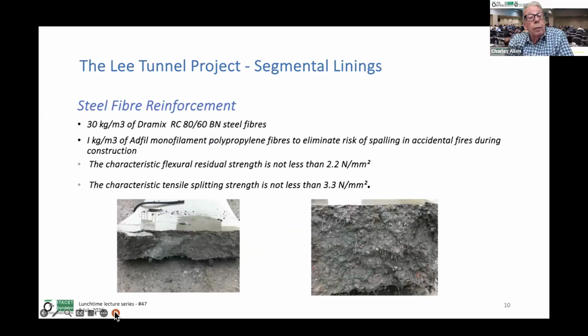The steel fibre reinforcement, we only used 30 kilos of Dramix 80/60 BN steel fibres. We used 1 kilo of Adfil monofilament polypropylene fibres. This was to eliminate the risk of spalling in accidental fires during construction. Obviously, we were not subject to road or rail fire curves. And the characteristic flexural strength was not less than 2.2, and the characteristic tensile split strength was not less than 3.3. Obviously, one of the first things we did during initial production was to break a couple of segments in half and look at the fibre distribution, which was very good. And so we didn't have to do that anymore.